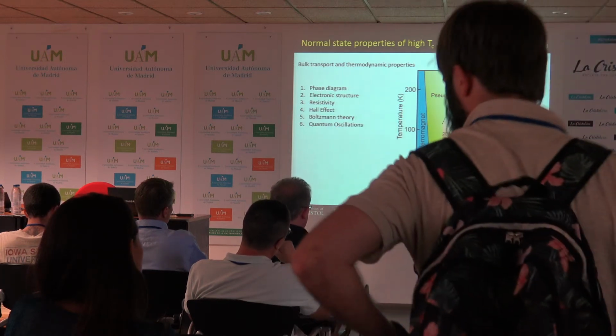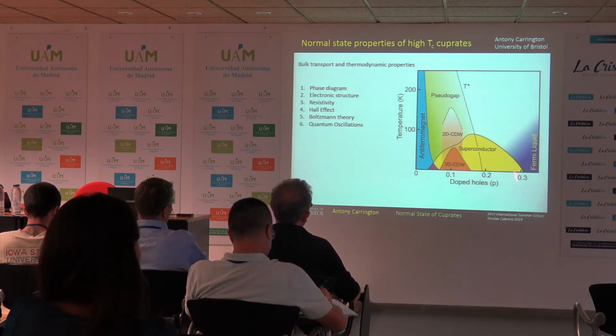Okay, so what's found experimentally is that this thing is an insulating antiferromagnet. So different to the iron-based case, where it's a metallic antiferromagnet, here it's an insulating antiferromagnet. And as we dope this, the antiferromagnetic ordering temperature falls to 0. In principle, there should be a quantum critical point somewhere there. Whether there is or not is open to conjecture. But anyway, at that point it becomes metallic and a superconductor. And it has this sort of dome of superconductivity with some little nicks in the dome here and there. And there are some competing phases. Okay, so one is called the pseudo-gap phase, and one is a charge density wave. And then right over here, which we call the overdoped regime, there is evidence that the material behaves as a normal Fermi liquid, with some caveats, as we'll come to in a bit.